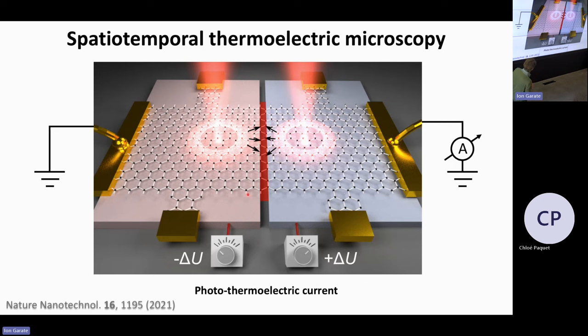And then what we're going to do is specifically look not at just the photovoltage created by the left pulse or the right pulse, but at how the heat from the left pulse affects the heat from the right pulse and how that generates a photovoltage, because that way you have a start-stop type of experiment where you can look at diffusion.